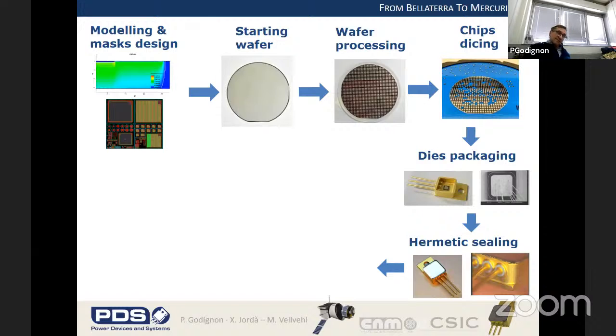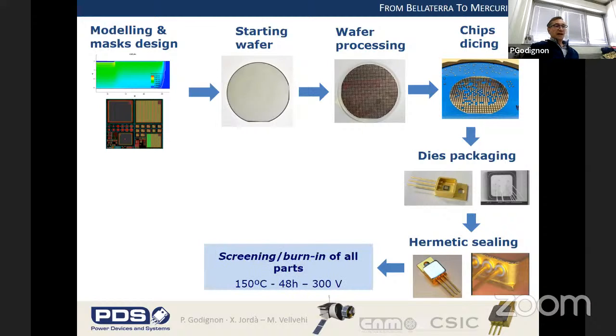Okay, so after this packaging phase, we have the final component ready. And then we have to check, after all these steps of processing, if the component is still proper for the application. And we have to go through a so-called screening or burn-in phase. So all the parts must follow this stress. Each stress is defined for each kind of device. So in our case, we use 150 degrees C, 48 hours biasing at 300 volts in order to try to see some defects inside the produced devices.